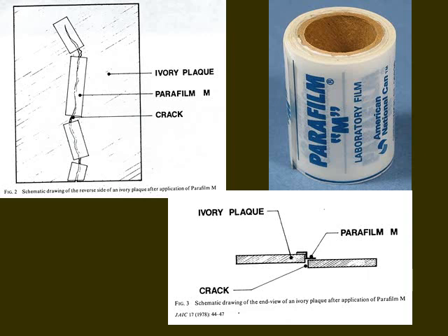In 1978, the Walters Art Gallery experimented with repairs to reinforce cracked ivory plaques. Several plaques in their collection exhibited cracks that extended almost their entire lengths, and because of warpage, the ivory on either side of the cracks did not meet at the same level. The front surfaces of the plaques were carved in relief, and the reverse surfaces were polished smooth. Because the objects needed to withstand fluctuating relative humidity levels during traveling exhibition, a method of reinforcement was needed that would support the plaques while yielding to ongoing dimensional changes.